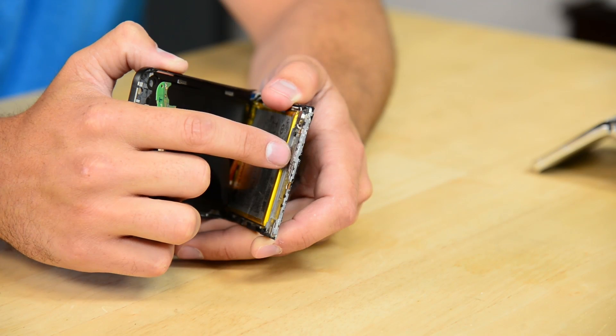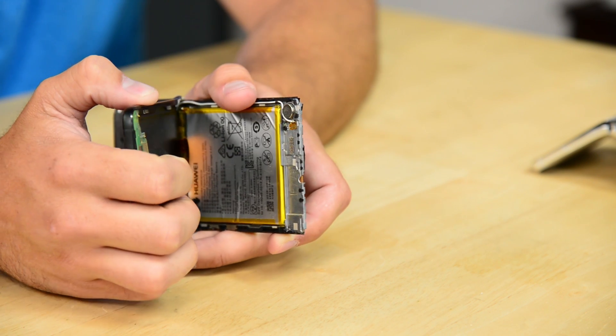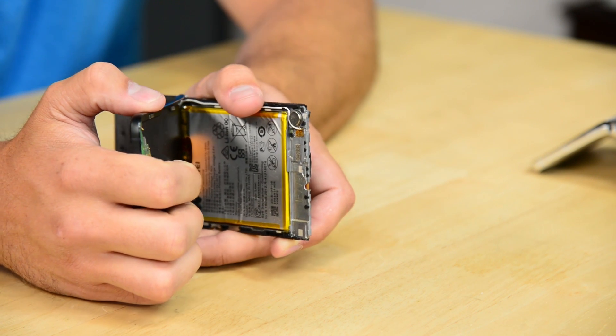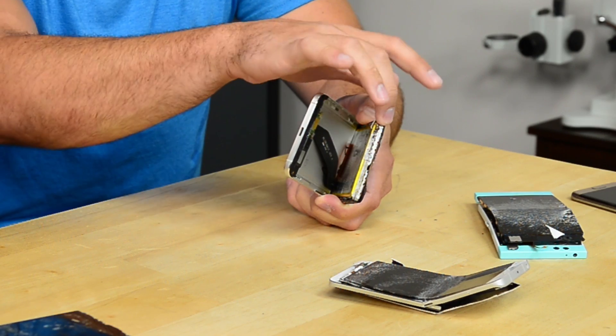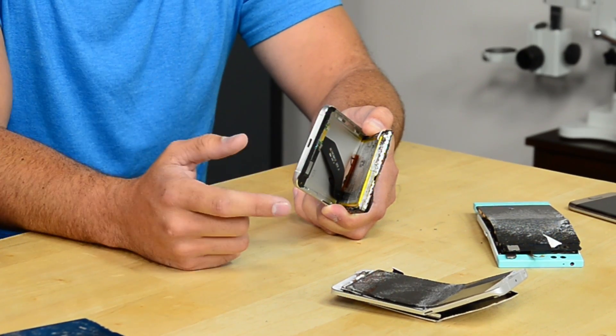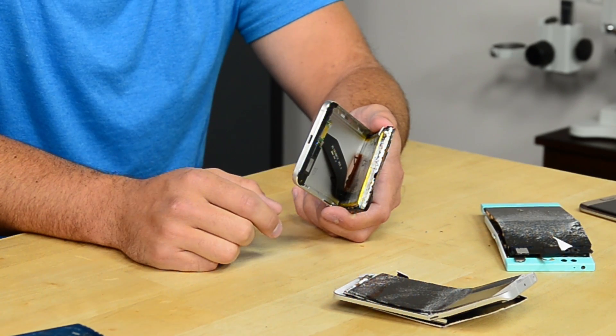So what happened here? I think they tried to make this a relatively durable phone. They have a pretty thick piece of metal in the center of it. The only problem is that on the edge of the metal they joined it with plastic using these little dovetail joints. They screwed the back panel directly into the plastic, which is a fragile piece. The reason this one broke is because all of those little dovetail joints snapped and then it just kept going after that.